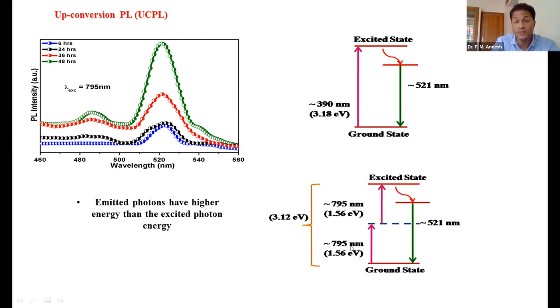So the two photons having small energy, 1.56 and 1.56 eV, are absorbed simultaneously, and the system reaches a higher excited state. Finally it comes back to the top of the conduction band, and from there it relaxes to a lower energy state and liberates a photon having an energy corresponding to 521 nanometer. So the reason for this upconversion photoluminescence is two-photon absorption.